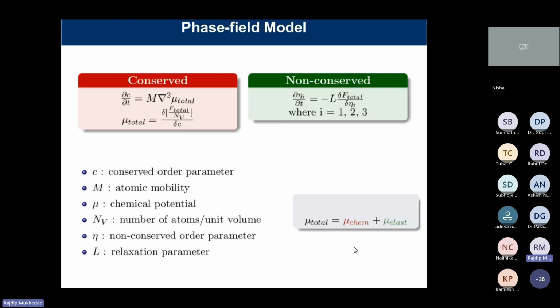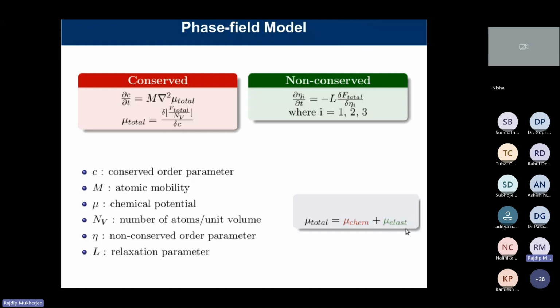So μ total in solid state phase transformation, the chemical potential, may have a chemical part which is coming from the bulk free energy. It may have other things like elastic parts, because there are lattice parameters which may be different between the defined phases. So elastic strain can be involved. There may be external stresses also. So generally in solid state phase transformation we need to calculate the chemical potential due to elasticity, right? But if you want to calculate the effect of a magnetic field, then there will be another μ magnetic, right? So the chemical potential will have several parts.